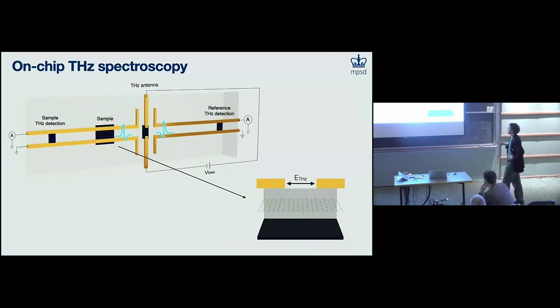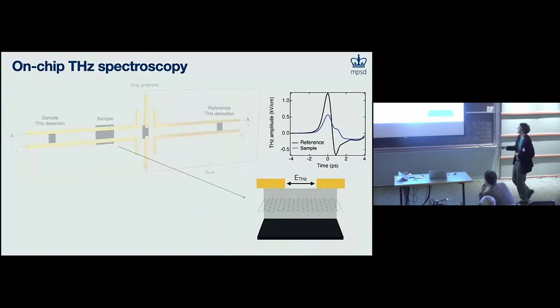So we do the experiment. We photoexcite this central switch. This is the empty reference arm. This terahertz pulse, when it passes by, shakes the carriers in our sample, modifies that pulse, and then we can detect these downstream in parallel using these two photoconductive switches. So here's what our data looks like. You can see the black trace. This is the reference trace. This is what propagated to the right. It's just a nice, clean, single-cycle terahertz voltage pulse.